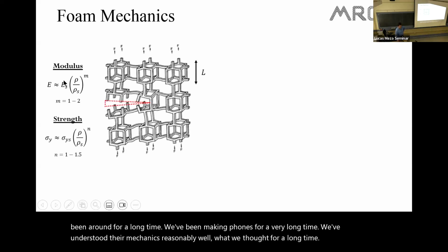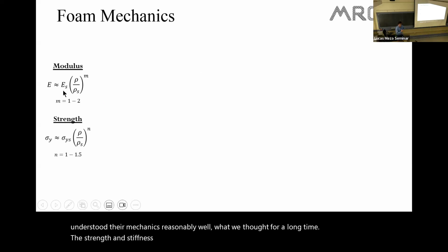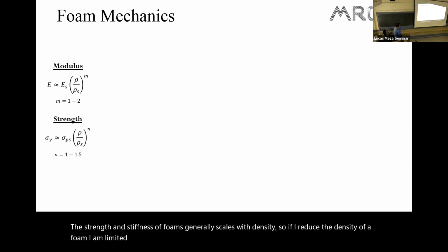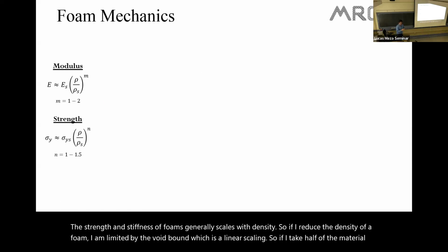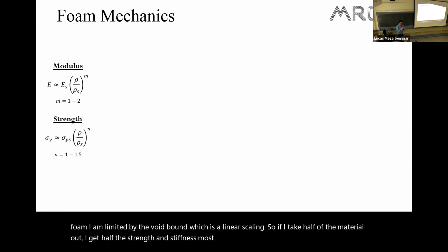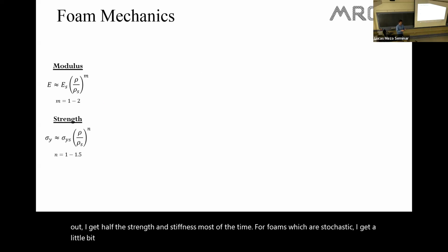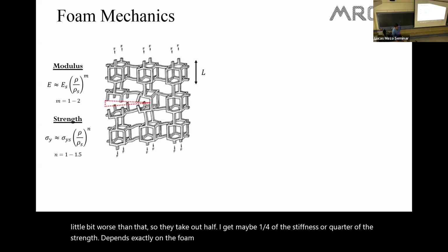The strength and stiffness of foams generally scales with density. So if I reduce the density of a foam, I am limited by the Voigt bound, which is a linear scaling. So if I take half of the material out, I get half the strength and stiffness. Most of the time for foams, which are stochastic, I get a little bit worse than that. So if I take out half, I get maybe a quarter of the stiffness or a quarter of the strength. Depends exactly on the foam architecture.